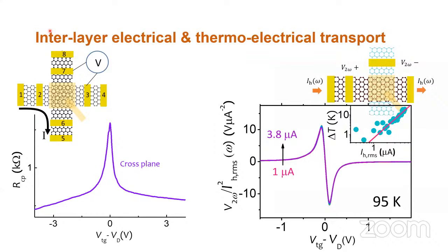Normally, what we do is measure the 4-probe resistance of the two graphene layers to measure their temperature. Why I believe it is unlikely to be a temperature difference within the same graphene layer is because within the same layer, the thermal conductivity of graphene is extremely large, nearly 5,000 watt per meter per Kelvin. So it's extremely hard to retain a temperature difference of such a large number within a single layer. So I doubt it is a temperature difference within the layer.